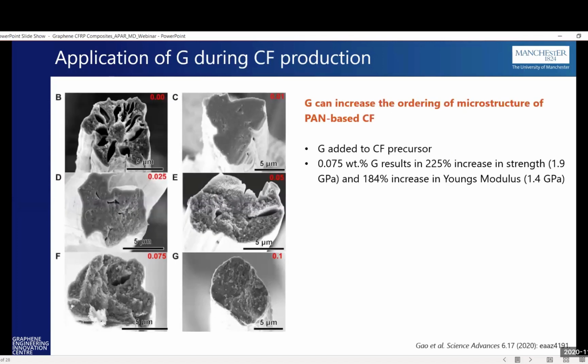Another interesting application area, which has seen a lot of press recently, and it's a very interesting piece of science that was developed earlier this year: by adding graphene to the carbon fiber precursor, that is polyacrylonitrile, you can actually improve the properties of the carbon fiber itself. This study has shown that by adding just 0.075 wt.% of graphene, the strength and the modulus increased by quite a way.